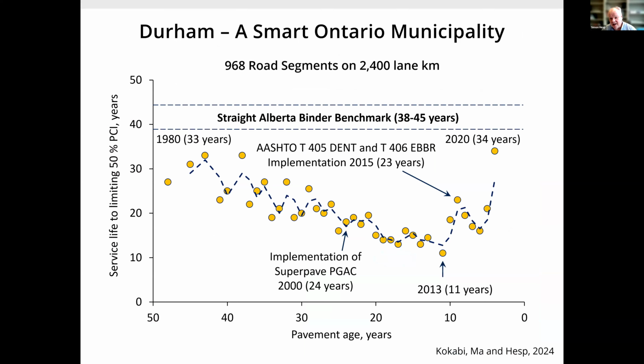Durham Region, a smart Ontario municipality. Dan Wechter and his staff, all of them extremely supportive. The regional council chair, extremely supportive. All the mayors in Durham, they understand the issue. This is about budgets. In 1980, we got about 30 to 40 years out of pavements. Each point in this graph is the average for about 25 contracts. Around 2013, this is the average of maybe 40 or 50 contracts. There's few from the 80s that are still around, but there are many from the 2013, 2010 range.